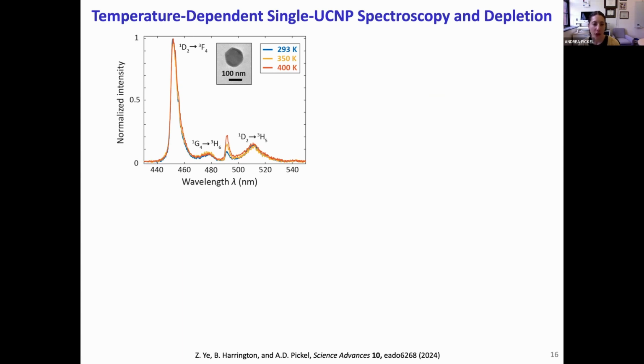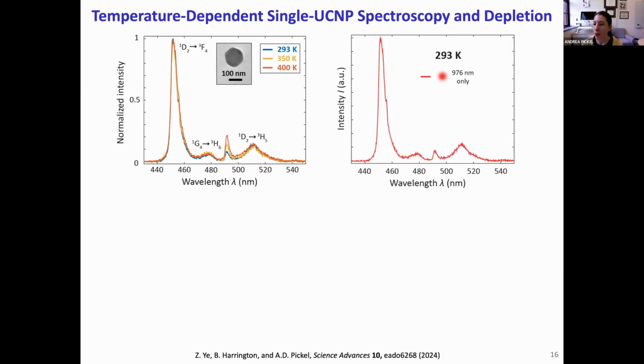So first we recorded single UCNP spectra at different temperatures with the goal of identifying temperature-dependent features, and we did indeed observe some temperature dependence. Next, we tested our ability to deplete all the peaks we observed. This is a room temperature single UCNP spectrum taken using only our excitation laser. And if we keep applying that same excitation power, and now we also apply our depletion laser as a Gaussian beam, we see that we can deplete the entire spectrum quite successfully.